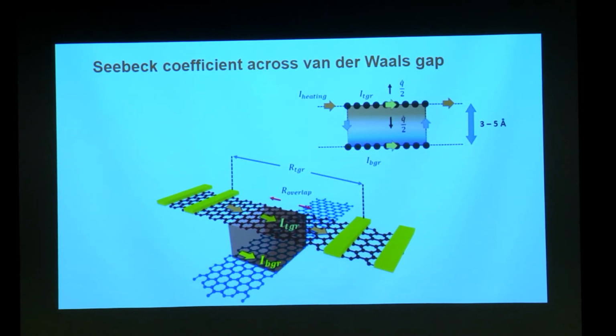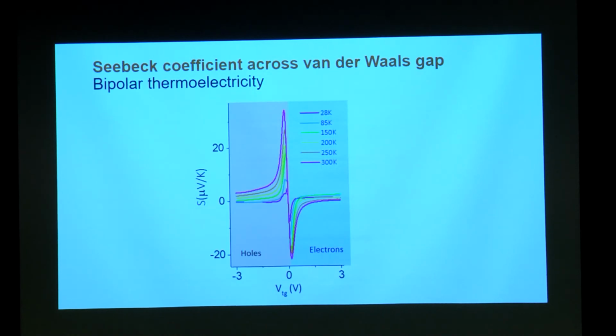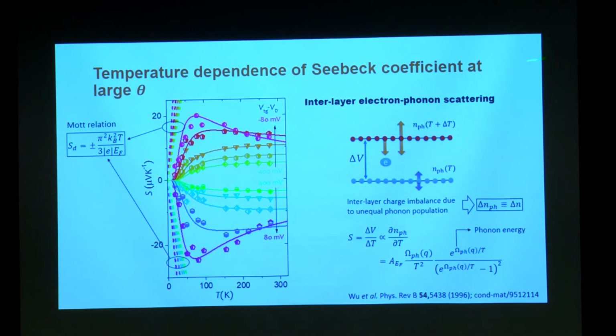And if you do that, we find something very interesting: if we heat up one layer and look at the corresponding voltage difference, which is the Seebeck coefficient across 3 to 5 angstroms, it depends extremely strongly on the angle between the individual graphene lattices. For example, this is the Seebeck coefficient temperature dependence at large angle, where you can see that instead of being directly proportional to temperature, as the Mott relation predicts it should be, it actually is very flat and saturates at high temperature, and it can be entirely explained by electron-phonon interaction at the two layers. The higher the number of phonons, the more it kicks the electrons out and creates a voltage difference between the two layers, and the Seebeck coefficient is described by the derivative of the Bose-Einstein distribution.